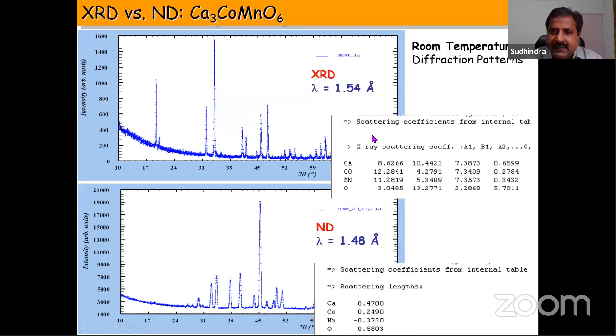One of them is that in the case of X-rays, the form factor comes into the picture, whereas in the case of neutrons, you have a scattering length. Again, cobalt and manganese being neighboring elements, their X-ray scattering factors are almost the same. What it means is that when you want to look at the cobalt and manganese composition, or see how much cobalt and manganese is there, it is very difficult to distinguish between them. They may look similar in X-ray diffraction. But if you look at the cobalt and manganese scattering lengths, you can see that for cobalt it is a positive b value, whereas in the case of manganese it is negative. So there is a clear contrast between cobalt and manganese, and you can easily identify how much cobalt and manganese is there. Particularly in this system, if you are working with the cobalt to manganese ratio, it is easy to distinguish them using neutron scattering lengths.